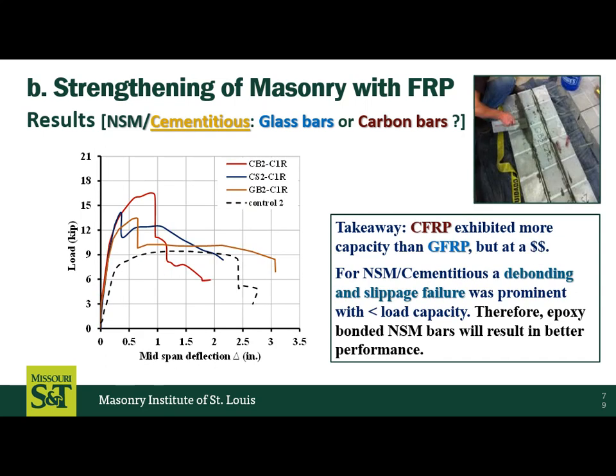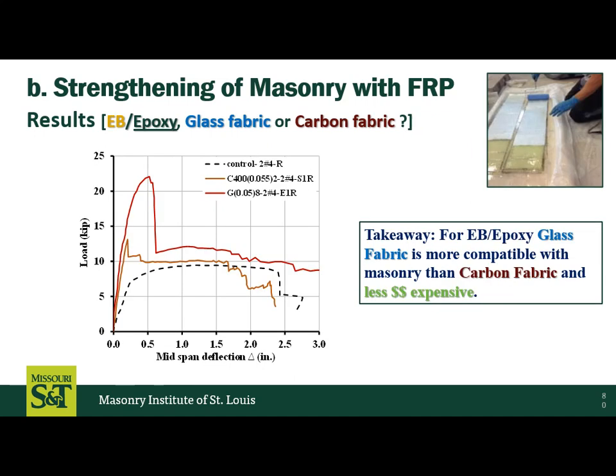If I look at near surface mounted now where I put cementitious in the bed joints, we get less capacity. And this is because of the way it fails. It starts to slip in the groove. And so our takeaway is, okay, probably cementitious material in a near surface mounted application is not as good as using an epoxy, okay? And, you know, I won't read those other details. Now, if we switch to externally bonded with epoxy and the glass up here versus the carbon, what happens here?